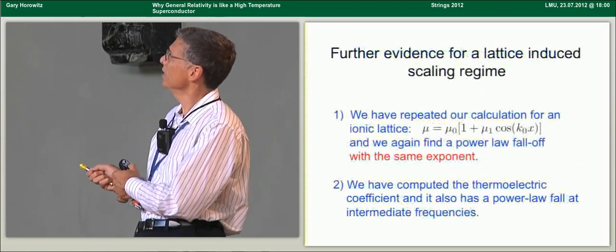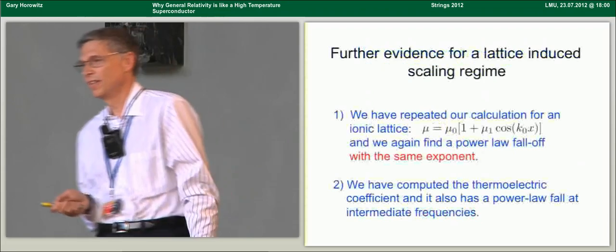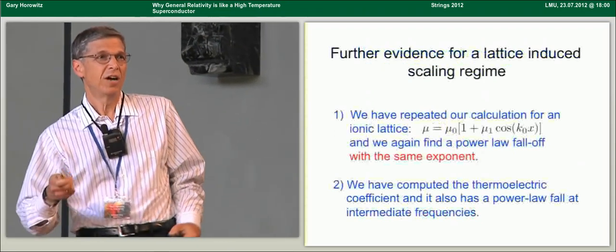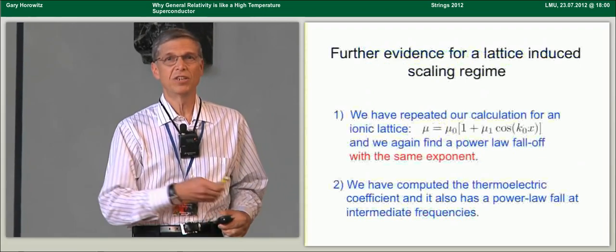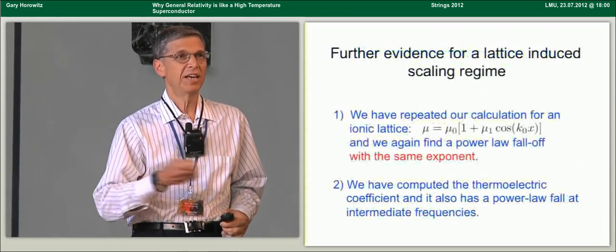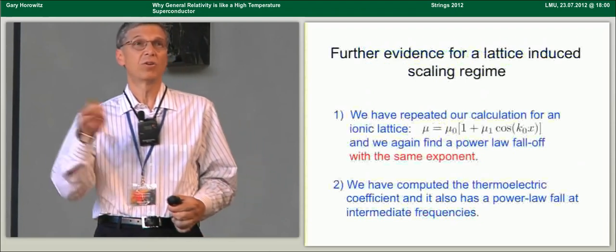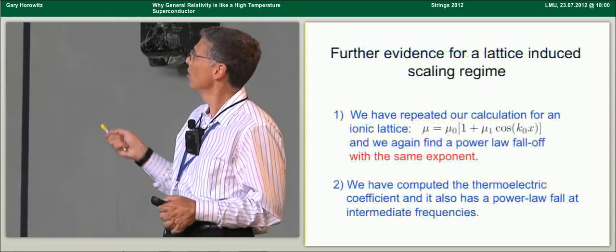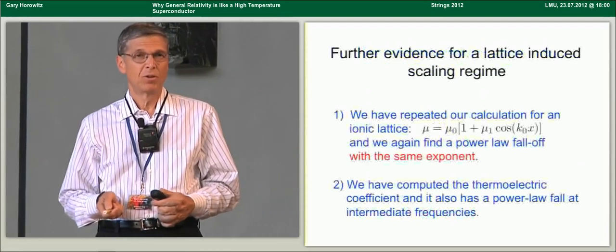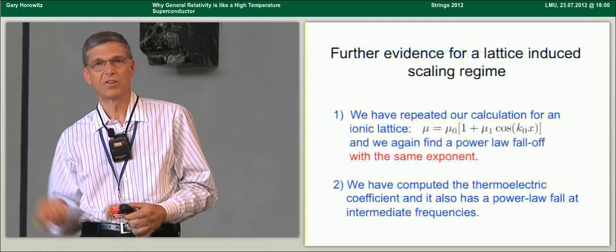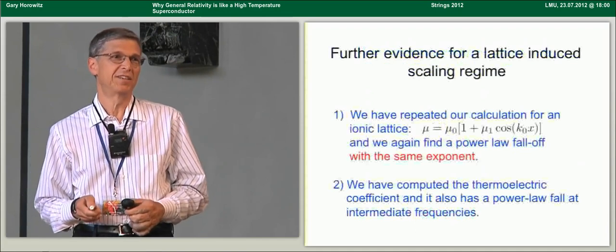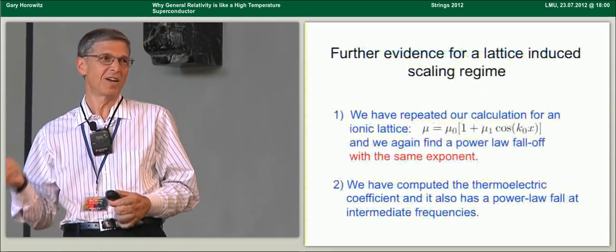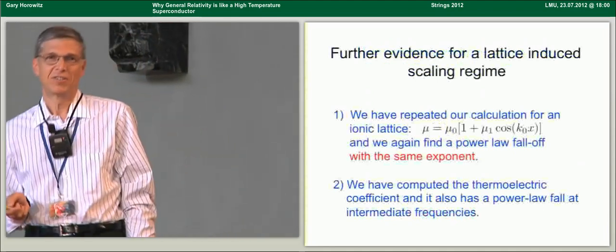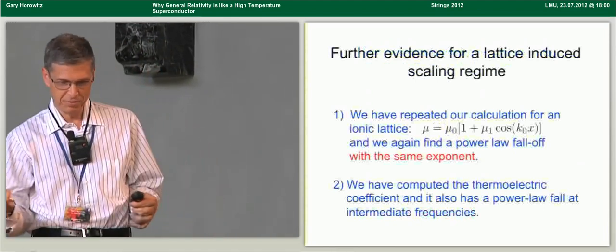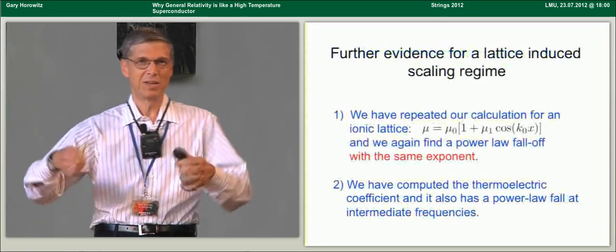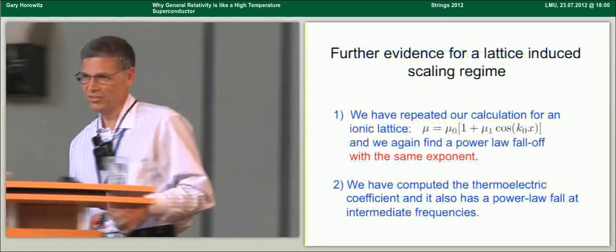Then we looked at the thermoelectric coefficient. When you apply an electric field, you not only generate electric currents, you can generate a heat current. So we looked at that heat current and found that it also has a power law fall-off at intermediate frequencies with an exponent, which in this case turned out to be 1 over omega to the 0.8. Needless to say, this is not something we can compare with experiment, because experimenters have a hard time measuring heat flow oscillating between directions at high frequency for some reason.